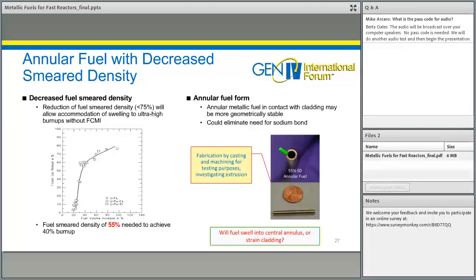Now the real question is what's the swelling behavior of this annular metallic fuel going to be? If it swells outward and begins mechanical interaction with the cladding right away and strains the cladding, that probably will be a feature that will limit burnup. What we were hoping was that the swelling would go inward into this central void, this annulus, and that it would be easily accommodated. But that had to be demonstrated by testing.